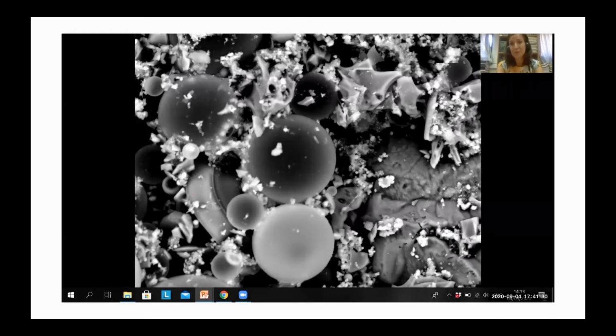This is a grout. It's an SEM image, so scanning electron microscope image, and it's a broken section. So it means it's a sample and it's not embedded in resin and cut to make a cross section, but it's the piece, let's say, as it is. So we can appreciate the 3D structure of it. And you can see that we have spherical particles, we have angular particles of different sizes. So these will definitely have an influence on the grout properties.